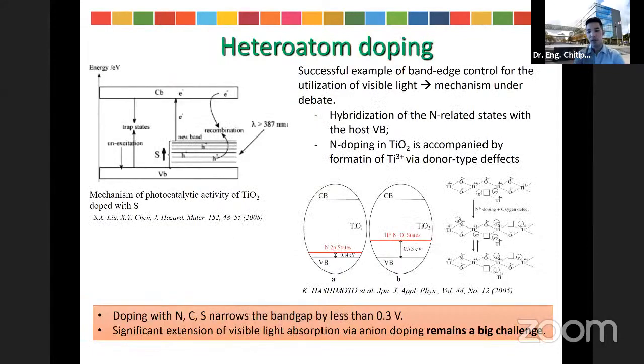So for heteroatom doping, the addition of dopants or guest atoms to the main semiconductor structure will shift the energy band gap by creating a new electronic state above the valence band or below the conduction band bottom. As a consequence, a lower energy is required to excite the electron from the valence band to the conduction band. In other words, doping can extend the spectral response of the semiconductor to the visible light region. Besides that, guest atom doping may affect the electron or hole trap, so it can reduce the recombination rate of the photo-generated electron-hole pair.